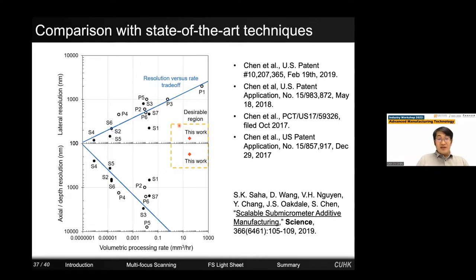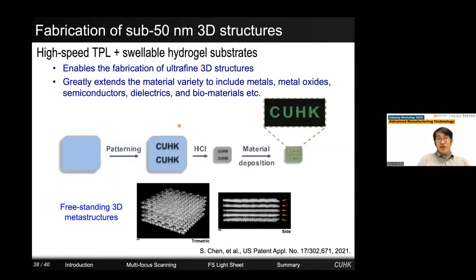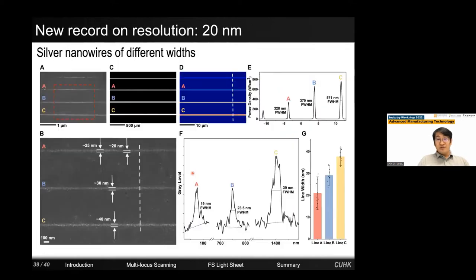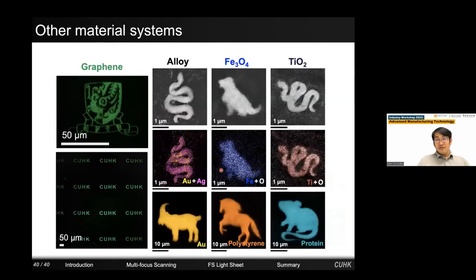With limited time, I can briefly talk about the idea. Essentially, we use a hydrogel as a substrate because hydrogel is swellable. So we print structures on the hydrogel in its expanded state using our light sheet system. After that, we follow with a material deposition process. And lastly, we can shrink the hydrogel by putting it into hydrochloric acid. As a result, we can create all these freestanding three-dimensional metastructures at 20 nanometer resolution, and you can see the resolution test to be less than 50 nanometers. We also tried different materials. The materials now include metals, metal alloys, metal oxides, semiconductors, or even biomaterials.